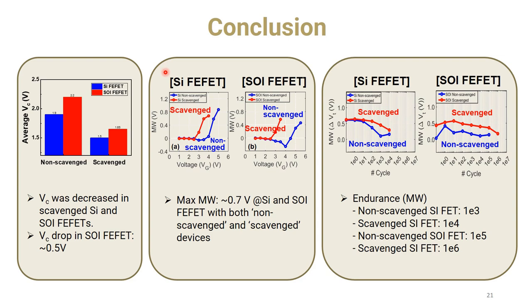The second thing is the memory window measurement. We see that in both silicon and SOI FEFET, the maximum memory window is around 0.7 and 0.8 volt. That is almost similar. However, the scavenging device needs a much lower voltage than the non-scavenging device. So that is also a similar trend in silicon and SOI FET.